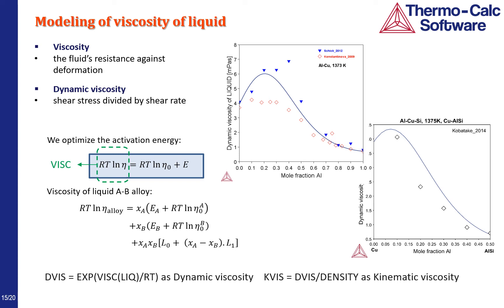Finally, I would like to show you recent progress in the modeling of thermophysical properties. For viscosity, we modeled the dynamic viscosity, but a converted term is stored in the database because this benefits extrapolation. For calculations, the software converts values back to dynamic viscosity. Kinematic viscosity is dynamic viscosity divided by density. The density can be easily calculated from the molar volume data available in our database. Here I show viscosity of aluminum-copper and aluminum-copper-silicon melts. Experimental uncertainties are usually large and can be up to one order of magnitude for viscosity.